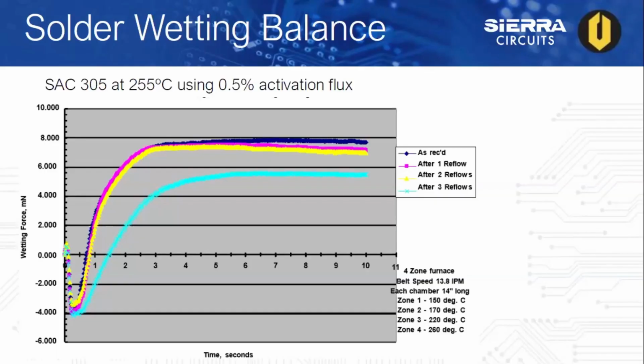The as-received sample showed the highest wetting force, and as you can see in the blue there, the sample after 3 reflows showed the least wetting force. But however, all the tests had acceptable results overall.